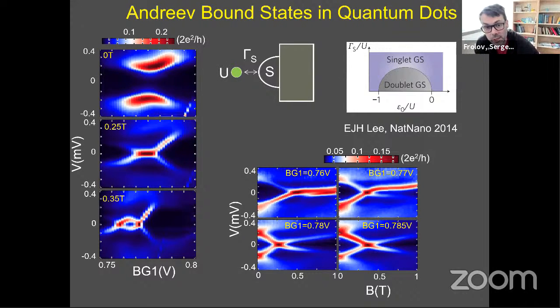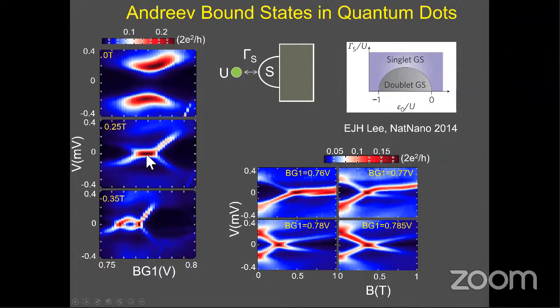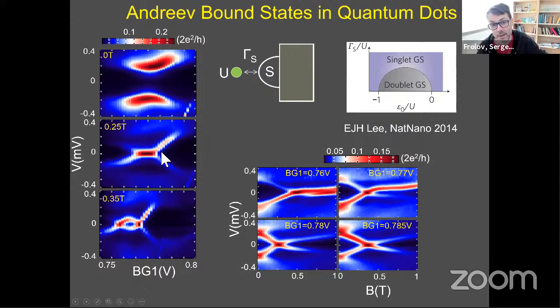And when we do transport measurements, when we tunnel into the nanowires, what we see is transitions between ground and excited states when we add one particle. So when the ground and excited states have the same energy, we will see that transition at 0 energy or at 0 voltage in the measurement. This is how it looks. So here, for instance, at 0 magnetic field, we have these bright states. That's the ground to excited state transition, or a resonance in tunneling at finite voltage. So nothing at 0 voltage, nothing sharp anyways. And then when we apply magnetic field, quarter Tesla in this case, that's when we hit the transition, the quantum phase transition, as a function of magnetic field in this case. And we have a 0 bias peak. It is relatively short, but it is there.